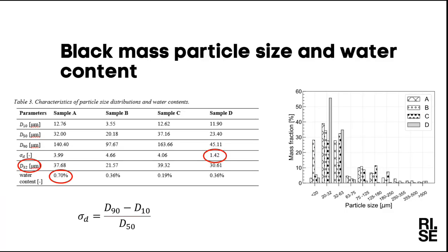And then we did some particle size analysis using the sieving method, and we have also calculated some parameters of the particle size, like the Sauter D32, the Sauter mean diameter, which is the diameter corresponding to the volume to surface ratio. Just one of the samples, sample B, has a lower number and the rest of the samples are very similar. Also, one of the samples has a lower value of this sigma D, which means it has more homogeneous particles compared to the rest of the samples. And also sample A has a higher content of water.